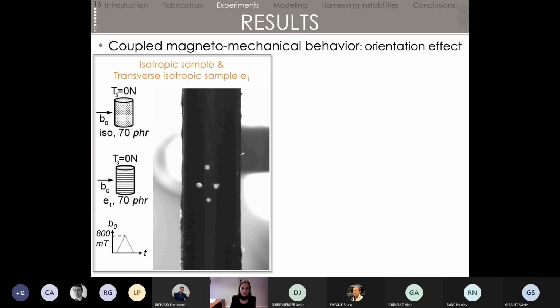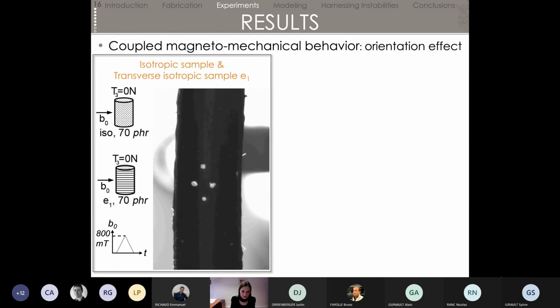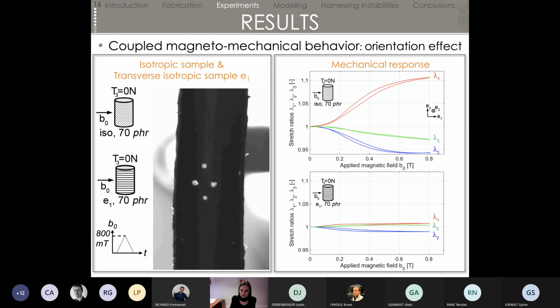The two samples that were not completely out of control, if we can say, are the isotropic sample and the transverse isotropic one, for which the chains are already in the direction of the magnetic field. So when we take these samples, and especially the isotropic one, and now we switch on the magnetic field, we're going to see an expansion in the direction of the magnetic field. So that's the magnetostriction that we were trying to measure.